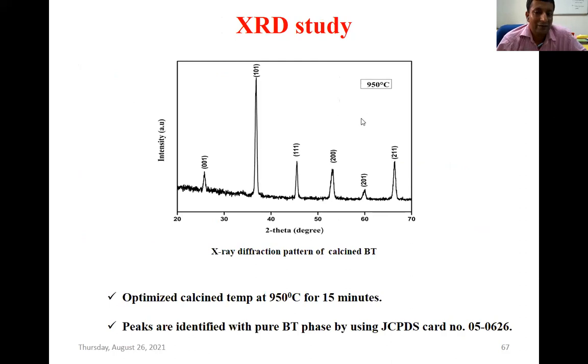And as I told, we are also processing the ferroelectric materials by high energy ball milling, and we have obtained this calcination temperature. Mind you, we are using carbonate and oxide powders, and normally the calcination temperature is near about 1300 degrees in the case of barium titanate, but we are obtaining single phase in 950 for 15 minutes. Of course, this is for the high energy ball milled powders, which are calcined via microwave. So this is about all of this.